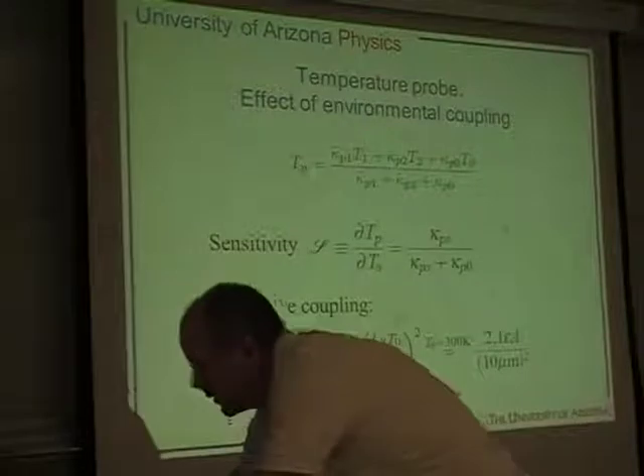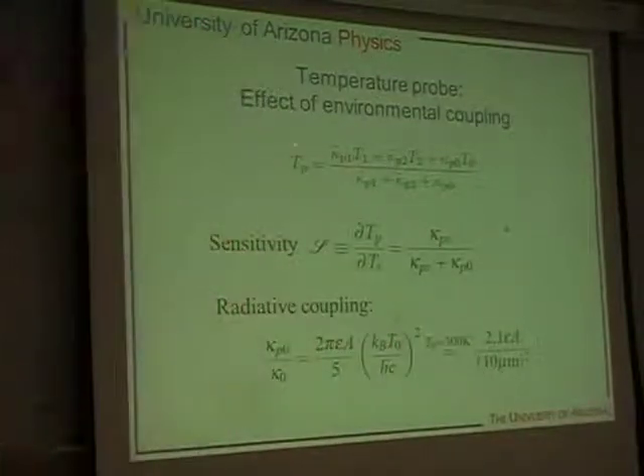So when I derive this formula for the temperature measured by the probe, this formula is completely general. Assuming that you can calculate these thermal conductances, including your electron-phonon interactions and everything, then this formula will still be true. But in the actual calculation I presented, we have not included electron-phonon coupling. I would say that in these systems, electron-phonon coupling is a weak effect. It's like a small perturbation on the electronic system. So I wouldn't expect it to be very important. Phonon energies are tens of meV.